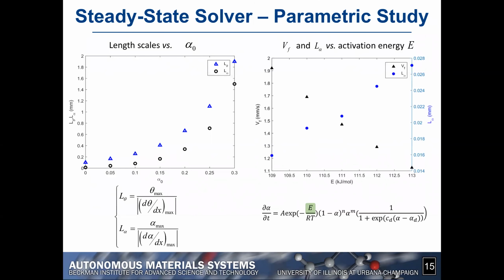We can also, using this model, capture the effect of, for example, one of the parameters that shows up in the cure kinetic model, which is the activation energy E, and we can plot the variation of the speed of the front and the variation of this length scale associated with the degree of cure front with respect to E, right? So these are ways to quickly make the link between the cure kinetics and the properties of the front. So that's for pure DCPD.